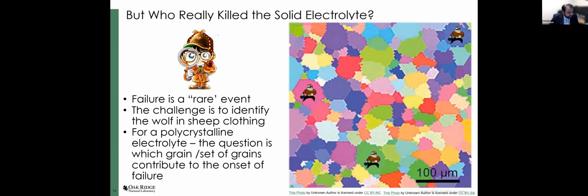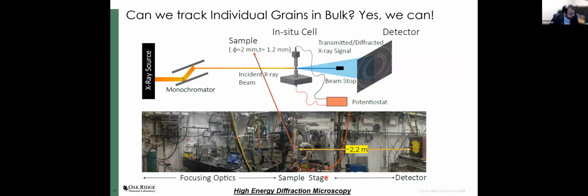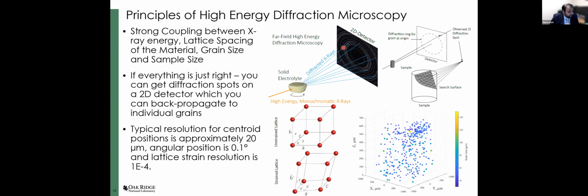And this is where I went to 1ID, and I did an internship with the materials physics and engineering group for a 6-month duration in 2020, where we were able to individually track grains in bulk polycrystals and track the chemomechanical responses as we cycle the electrolyte. So what you're seeing here is a schematic of a high energy diffraction microscopy experiment, as well as the experimental setup. What we do is we take our sample, put it in the beam, and collect diffraction images over a range of rotation steps, and then we are able to back out the diffracting grain centers of mass. We are able to extract the diffracting grains' orientation as well as lattice strain. And so this is a very powerful technique that enabled us to look at an entire solid electrolyte and each grain within that solid electrolyte.